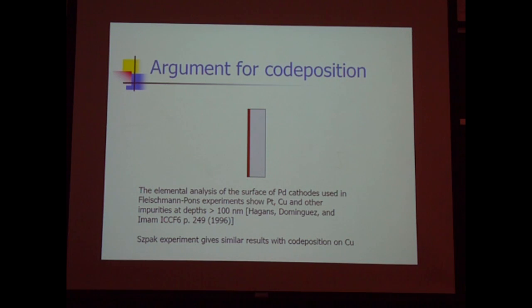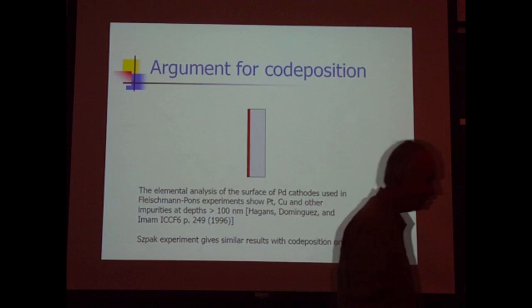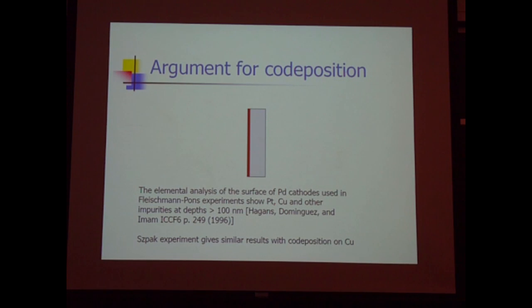You get some platinum coming off of the anode, and then you get co-deposition under the surface of the palladium. So you can actually see your co-deposited region because it's got some platinum in it. So the evidence from the surface analysis of platinum on the surface supports the notion that co-deposition went on in the Fleischmann and Pons experiment.